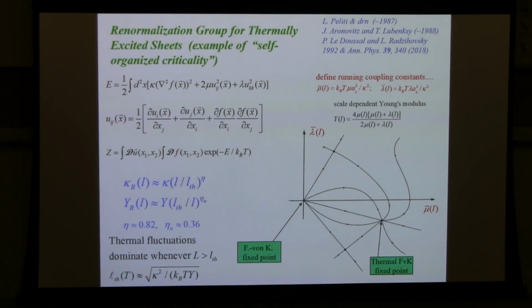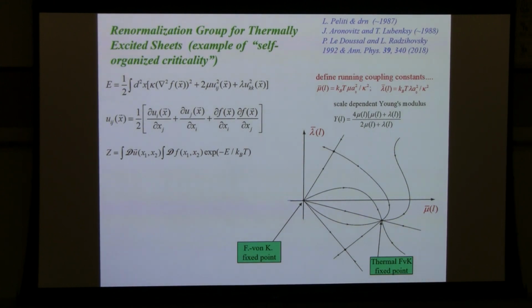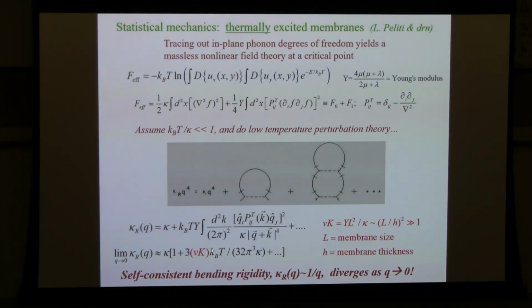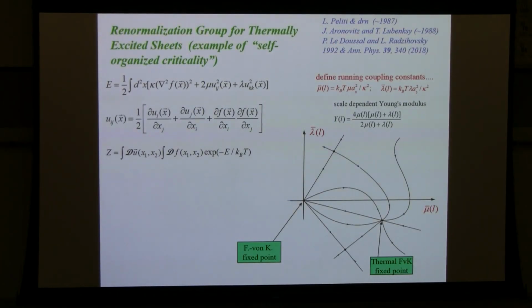And this is what I mean by kind of the death of Hooke's law for this class of materials that can fluctuate into the third dimension. The bending rigidity now depends on the scale. And there's a thermal length that tells you when that bending rigidity has to be looked at a little more carefully. There's an exponent eta, which is about 1, but details don't matter. But you can get a length scale, more importantly. It's kind of a Ginzburg criterion for this problem. You can ask when this correction is comparable to what it's correcting. And so that tells you there's a critical size embedded in this Foeppl-von Karman number, above which you better take the fact that Hooke's law has died seriously.